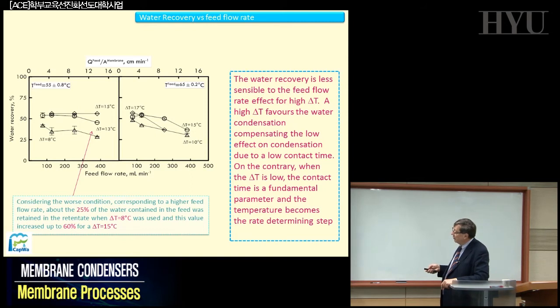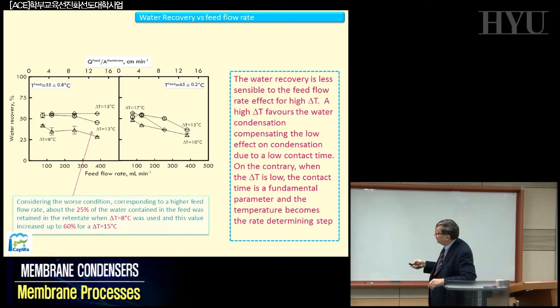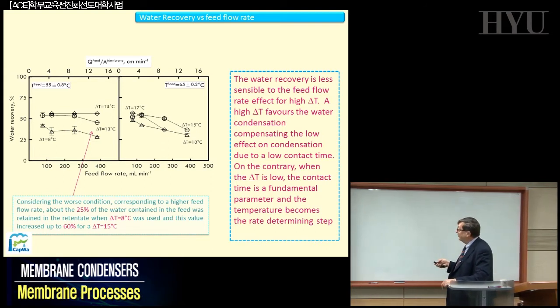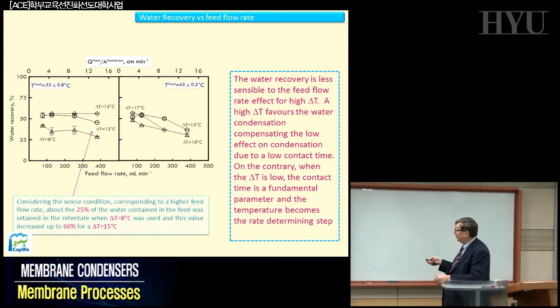So what is plotted here is the percent of water recovery as a function of the feed flow rate, but we recalculate the data as a function of this axial flow rate normalized to the membrane surface. And you can see here that the water recovery is less sensitive to the feed flow rate at high delta T, when delta T is significantly high. Here is 55, and this is 65. A high delta T facilitates the water condensation and compensates the lower effect of the condensation due to the lower contact time. So the two parameters can be integrated.